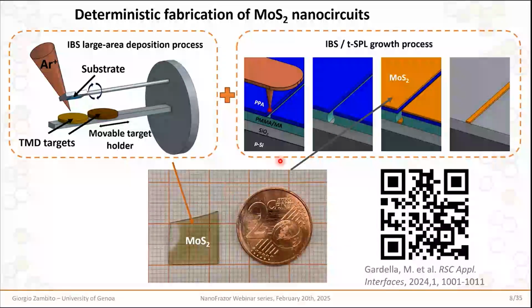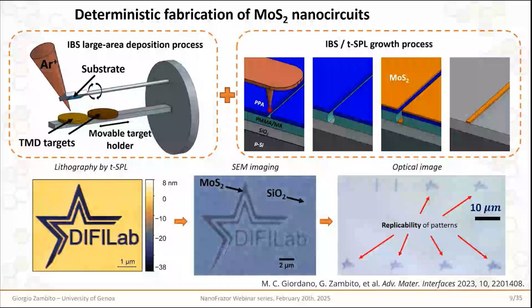So this kind of growth process combined with the bilayer liftoff by thermal scanning probe lithography allowed us to obtain a condition where we are able to homogeneously cover the whole substrate after t-SPL patterning, and after liftoff of the polymer mask, we are left with our nanogeometries, nanocircuits made of MoS2, for example. And as a consequence, we go from something like this. This is our facility logo embedded in PPA, as seen from the imaging capabilities of the NanoFrazor, and the resulting sample after the process I described, where these darker regions observed by scanning electron microscope are actually made of molybdenum disulfide. And that allows us also to get deterministic placement and replicability of these complex geometries, as you can see, which is something that usually with mechanical exfoliation is kind of difficult to achieve.